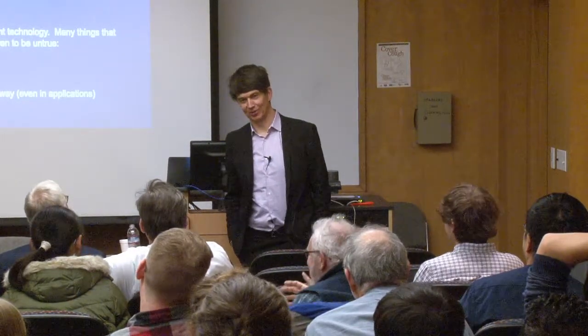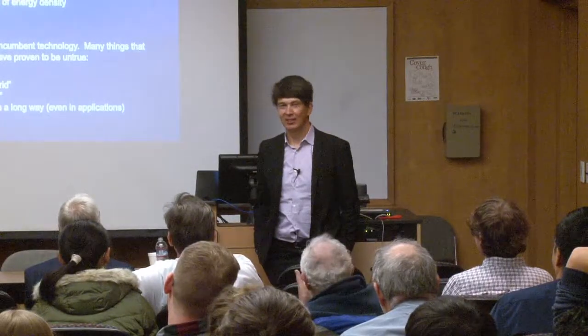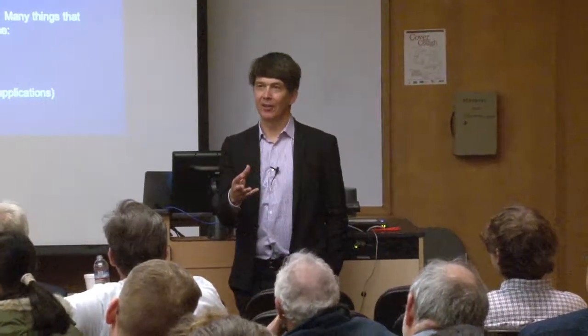More than we thought. When you start taking lithium out, you're doing two things, right? Obviously, you're creating a lot of vacant space, but you're also changing the valence state of the cobalt. You can think of it as p-doping. And obviously, these materials become highly metastable. But you're operating at room temperature, in principle. The fact that they're metastable is not a given that they will fall apart.